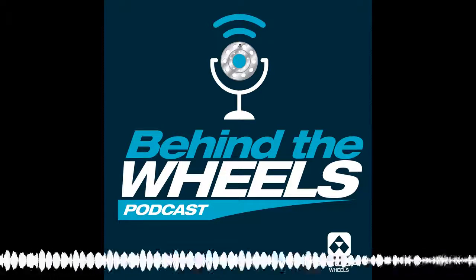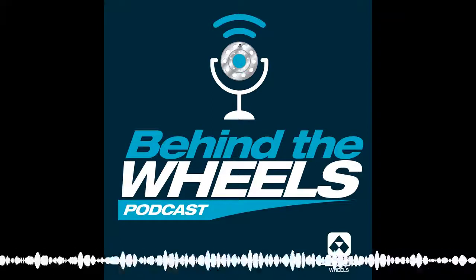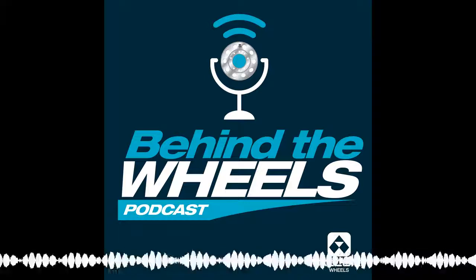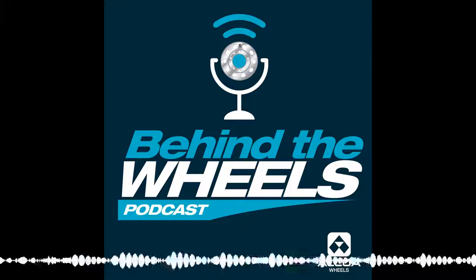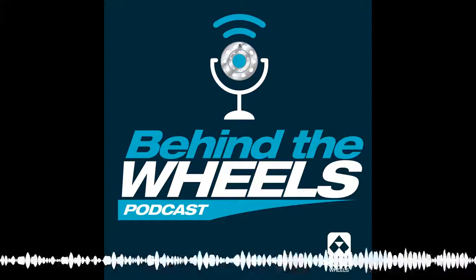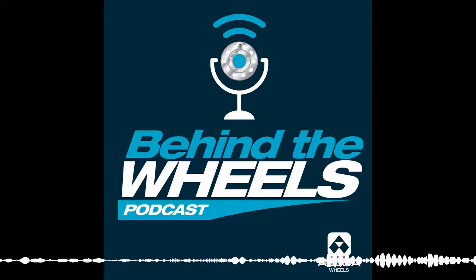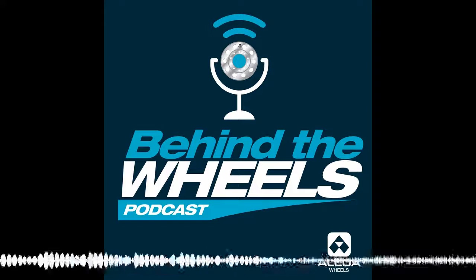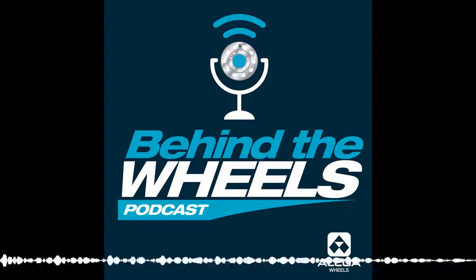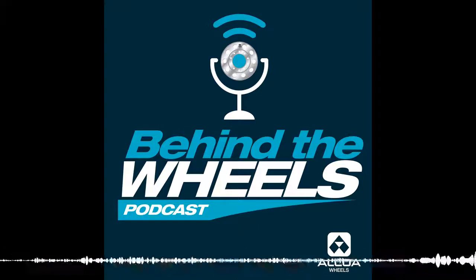Correct. The scientists who worked this up were able basically to create an aluminum oxide situation where you could transition from the wheel itself to the surface treatment that we're putting on, that then allows for a clear look, but also in a sense pre-corrodes it, but you can't see it. It's clear, and it keeps that surface bright. Obviously, the Durabrite name, without being just a surface coating that can then have corrosion that gets underneath the coating and grows, which people see. That's the difference between the surface treatment and a typical, let's say, acrylic clear coat type of coating.